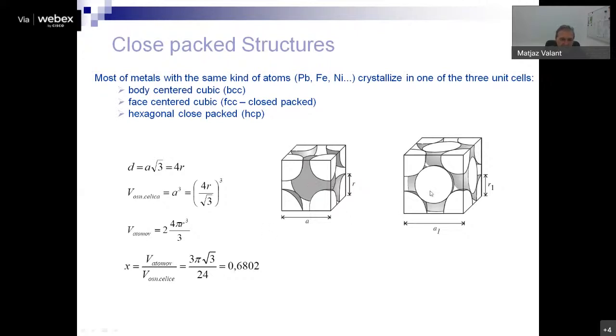Now, if we calculate that for the face-centered cubic system, which is a close-packed system, we will get, of course, a higher number. Well, I can leave you a homework to calculate this number for yourself, but I tell you, it's not very difficult. Just follow the same principle I showed you before. But the message here is that the close-packed structure has a higher space filling factor, about 74%, than the body-centered cubic cell. And the message is also that we can use very simple methods to calculate these things.